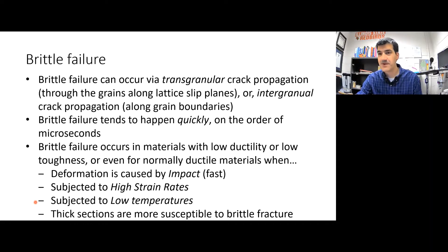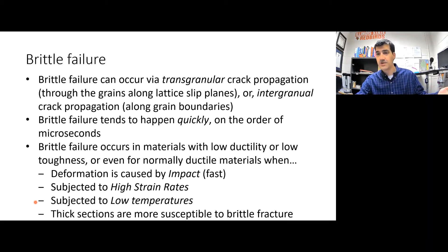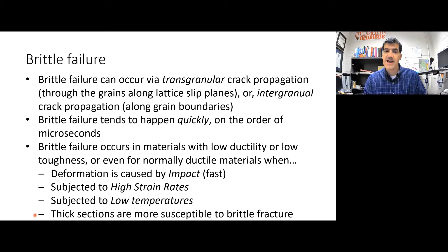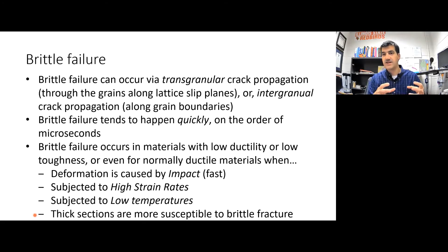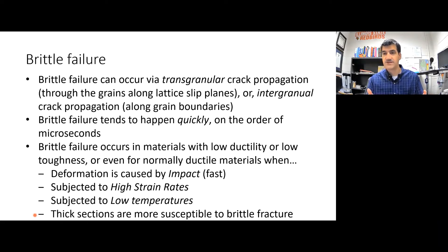If you have a real thick part, even though the material might be ductile, it's more likely to fail via brittle failure because the micro-voids inside don't have the ability to coalesce into a large void. If they're not able to coalesce, you won't get the ductile failure mechanism, so it's more likely the thick section will fail via crack propagation — which is brittle failure.